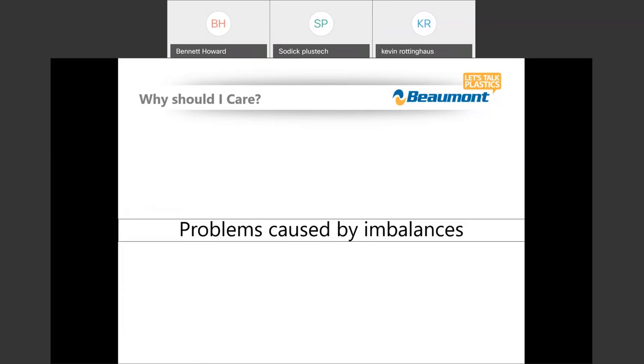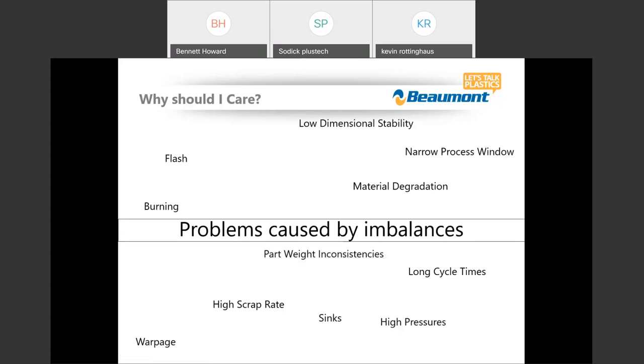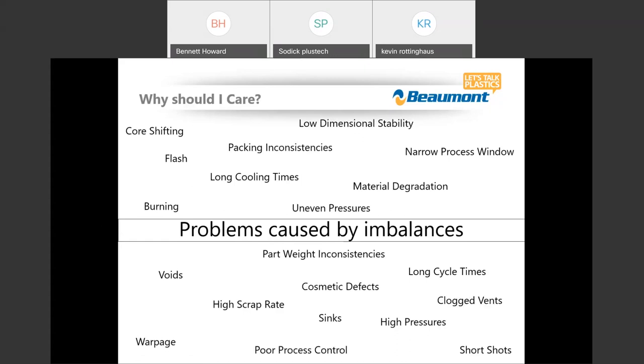is that everybody always ends up looking at balance, and it's one of the first things that we look at in a multi-cavity mold. Because there's a lot of problems that develop as a result of an imbalance. Some cavities have flash on them, other ones short shots, some parts have sink on them, while other ones are fully packed out. We end up with inconsistent weights, inconsistent packing, low dimensional stability, so we see our CPKs spread out. Longer cycle times, we'll get clogged vents in some cavities and not others. Some parts with voids, other parts that are burning while other cavities are not.